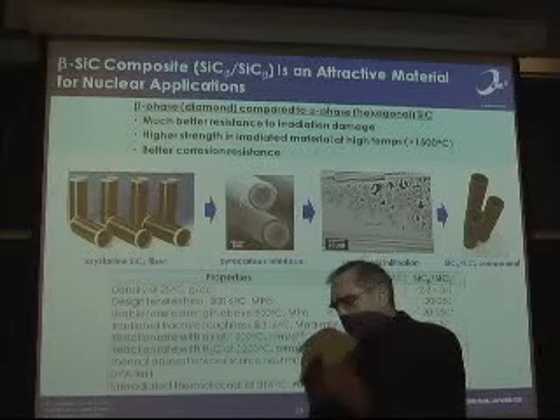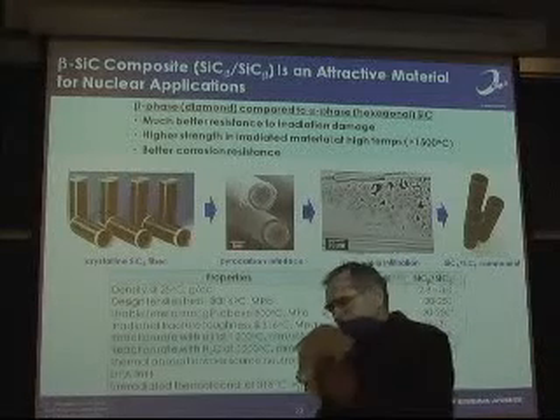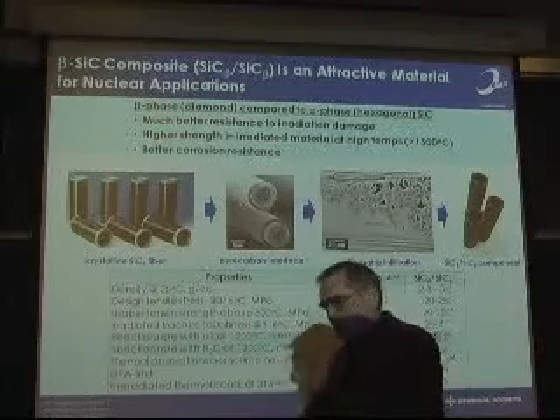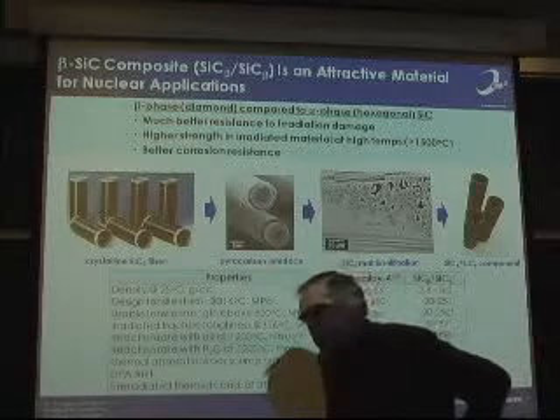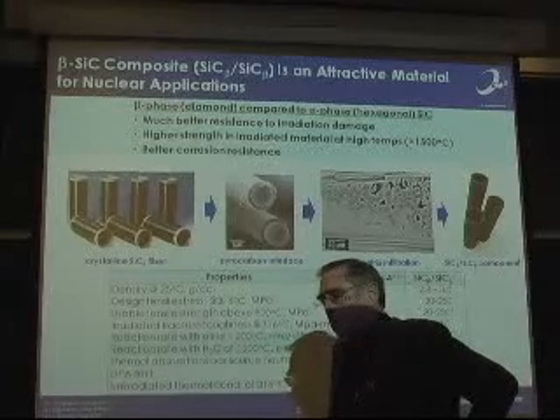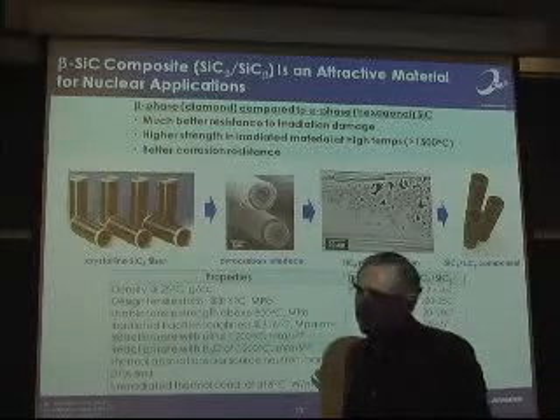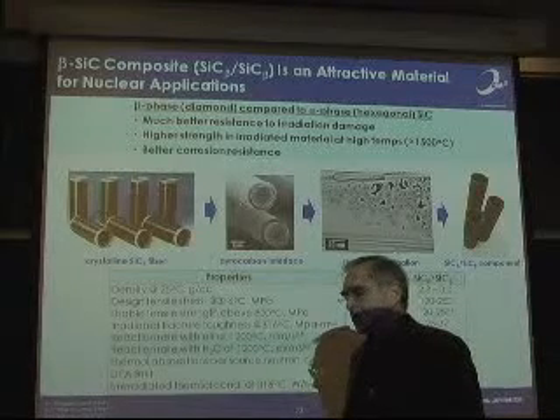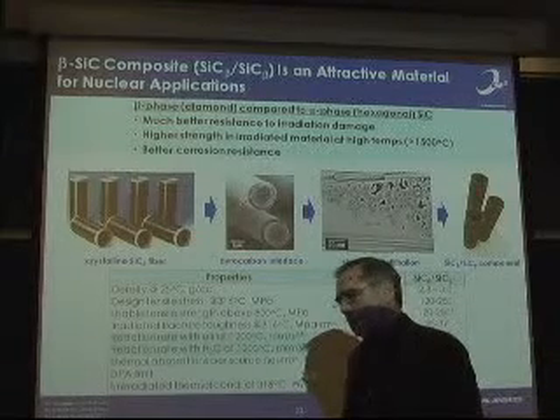What we have been able to achieve is a beta silicon carbide joint, where we use only beta silicon carbide material as the weld material, and within a few hours, we're able to produce a hermetic joint that is only beta silicon carbide that will sustain the radiation. That's one of the things that we claim as an achievement in our little program, and this has gotten some attention. There's no pressure buildup in the rod because you're venting all of the fission gas.